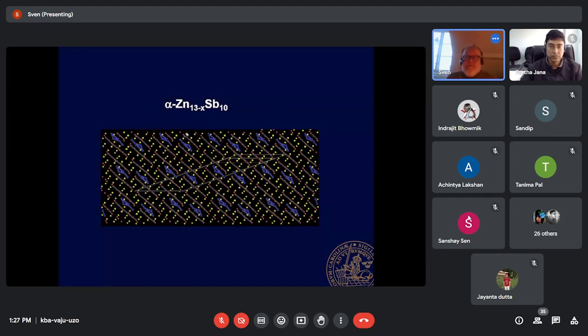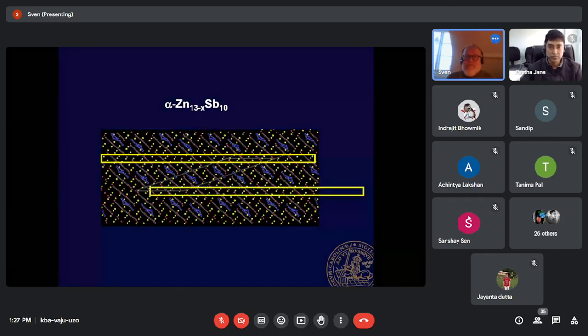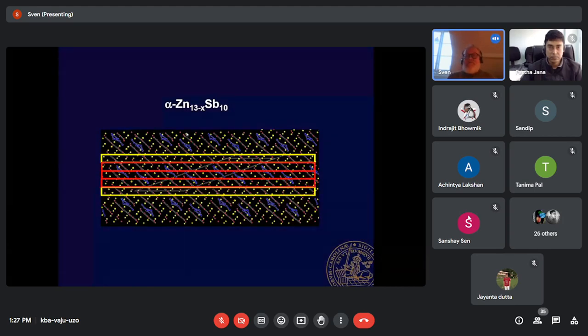That is actually occurring as slabs in the low temperature phase. And then there's another slab here, whereas the ordered interstitials live in 3 consecutive slabs. This is why it's a fourfold superstructure that you look at. Now, what makes this a little bit complicated is that not only is this